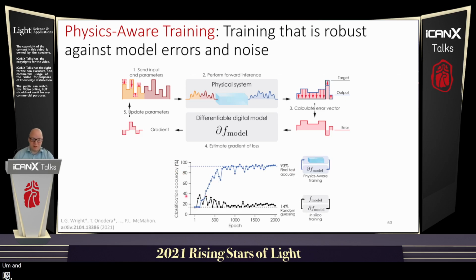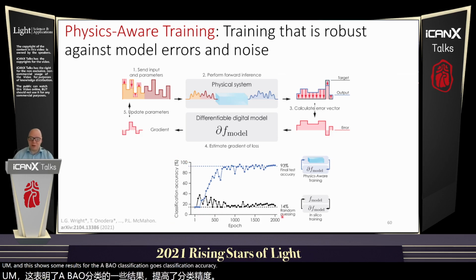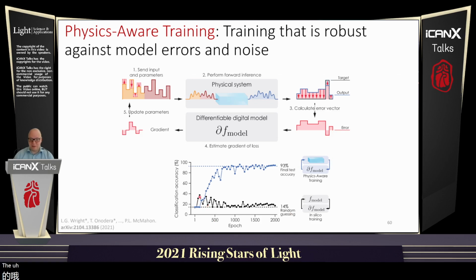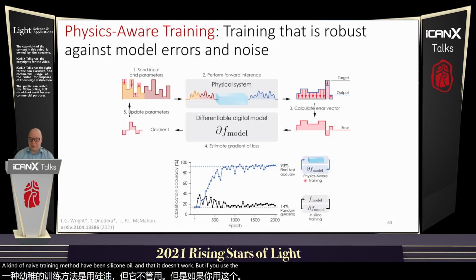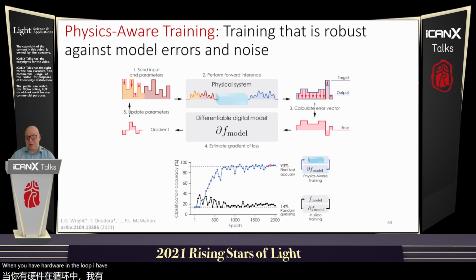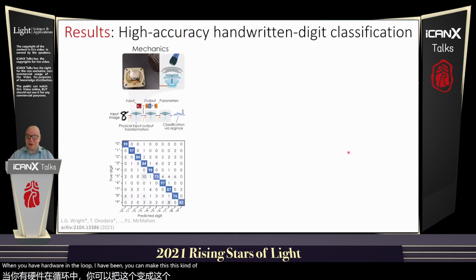And this shows some results for the vowel classification. Here's classification accuracy as a function of the training epoch. And what we can see in the blue curve is that our system is able to achieve 93% accuracy using our training method. The black curve here is showing that if you only use a naive training method in silico, it doesn't work. But if you use this method that we developed, where you have hardware in the loop, then you can make this scheme work.